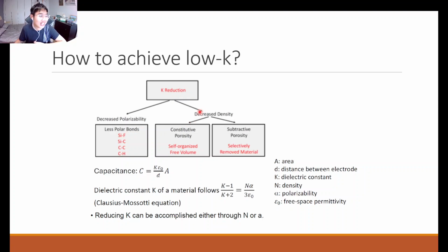And the second way is to simply decrease the density, have more pores in your material that are filled up with air, because air has a very low dielectric constant, right? So we can have a constitutive porosity. That means the material is in such a way that there's a low density and high porosity. For example, we may have a polymer chain that has a very large free volume. A polymer chain that is very bulky, has many side groups, that in itself forms a very low crystallinity, low density material. So that is constitutive porosity. There's also the idea of subtractive porosity, that we somehow remove material to create pores artificially in the material, which is also pretty hard to achieve, but it can also theoretically be done. And so therefore, we can achieve our low-K dielectrics through these two main methods.